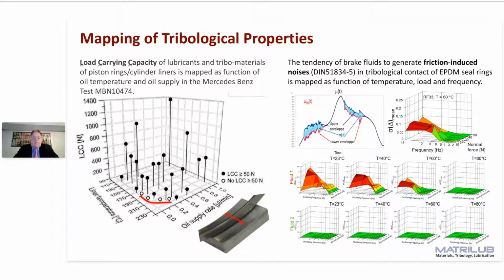What do you see now? The lower fluid, under any test conditions, has low sigma values because the light blue surface is more or less non-existing. The red fluid, when the vehicle is cold, tends to make noise. And when the fluid heats up above 80 centigrade, you have no noise. The consequence is, if you would test only at 80 centigrade, you conclude both fluids are good. But in reality, fluid number one makes noise when it is cold.